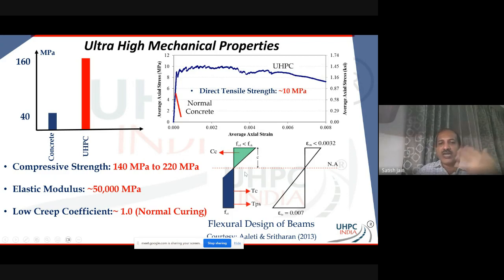And below the neutral axis, you take this strain hardening portion from the top and you put it down below, and that gives you a great flexural capacity. Okay, now that can be used as part of the design, and therefore you can really reduce your rebar quantities enormously in UHPC elements, right? So that's a big advantage that comes by reduction of these